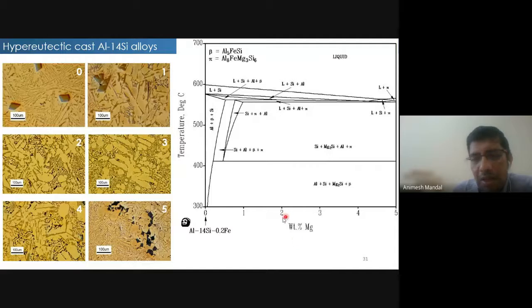That means what this particular study shows is that if you keep on adding magnesium to your hypereutectic aluminum silicon alloy, remember, the hypereutectic aluminum silicon alloy contains primary silicon. Sometimes, from a mechanical property point of view, it's not desirable. So the study was carried out to see if we keep on increasing the amount of magnesium in this alloy, what is going to happen to this primary silicon.